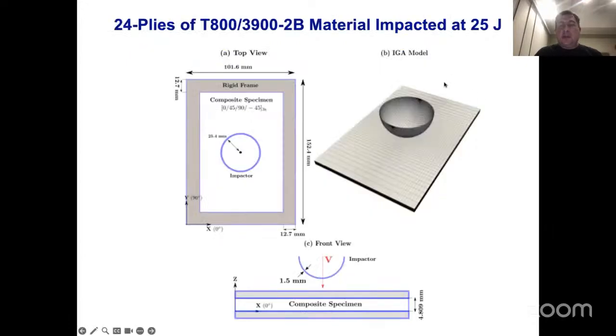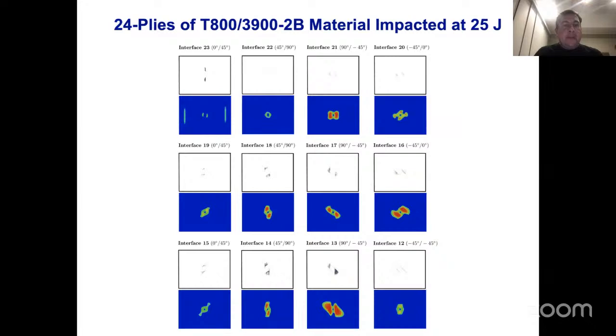Here's a different problem. 25 joule impact. In this case, the composite specimen has 24 plies. This is starting to get quite expensive for traditional finite element simulations. The impact tests were done at the University of California, San Diego, by my former colleague, Hyun Kim. They were able to measure delaminations through CT scanning.